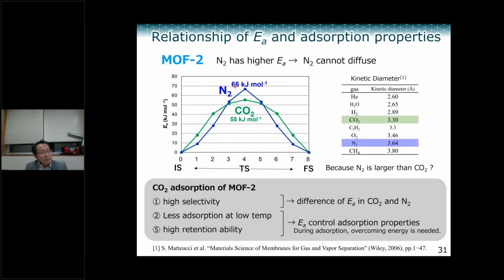The origin of this difference probably comes from the kinetic diameter, because CO2 is 3.3 angstrom and dinitrogen is 3.64 angstrom, which is slightly larger than CO2. Because of this difference, this MOF actually has a very nice selectivity for them.